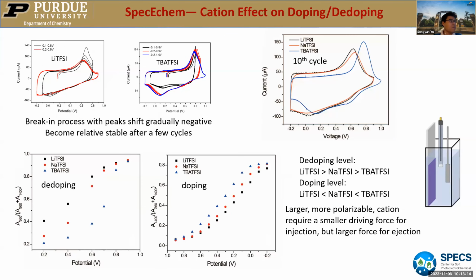I also compare the CV of this one. All these polymers require a break-in process. So we just run the different CVs, and after a few cycles the CV will stabilize, as shown here. The peak height almost does not change, both for lithium TFSI and TBA TFSI.